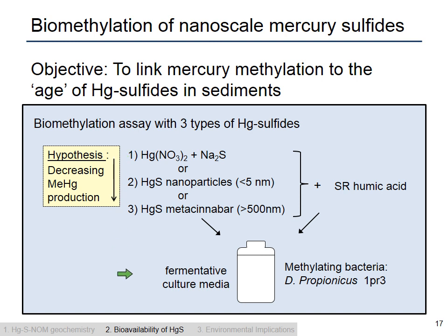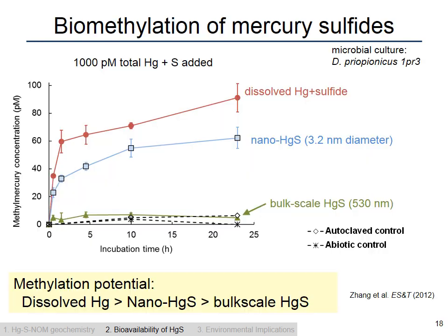So our initial set of experiments tested this with a pure culture, and then later on I'll show you results where we did the same experiment but in the sediment microcosm setting. Okay, so here's the result of the pure culture experiment. Again, we have our fermentatively grown sulfate-reducing bacteria that can methylate mercury, and we expose it to either dissolved mercury, nanoparticulate, or bulk scale particulate.